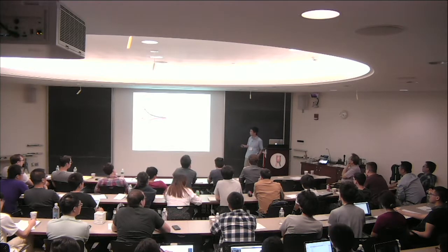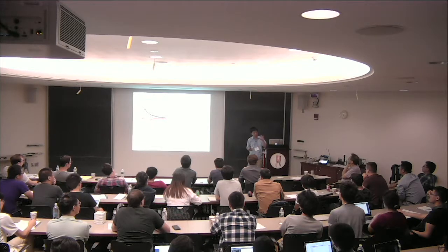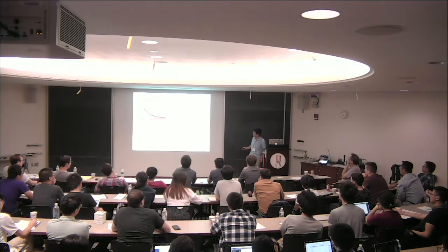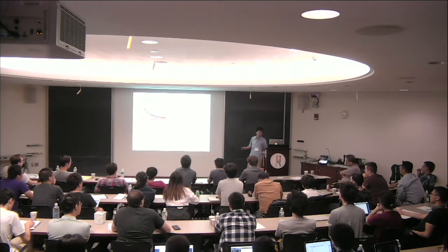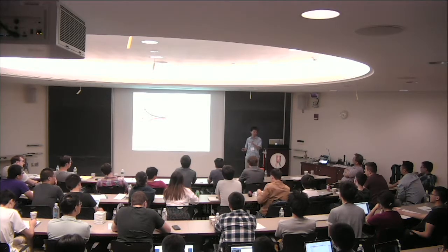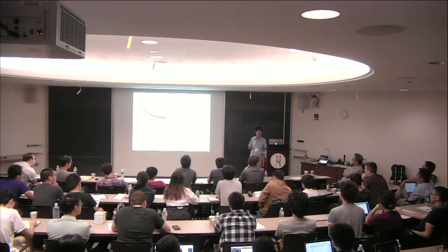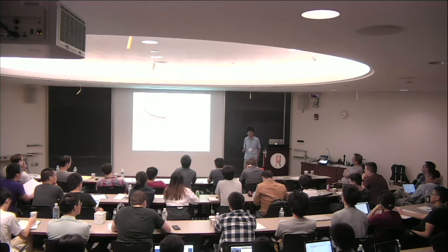So in order for them to go there, you do need a slightly finite momentum. If it's exactly at the K point, it is indeed forbidden. But even if you have a very small deviation of momentum, it becomes allowed, and that will limit the lifetime to a few to 10 picosecond range. Yes, that's a very good point.